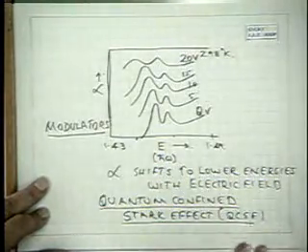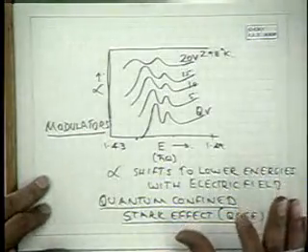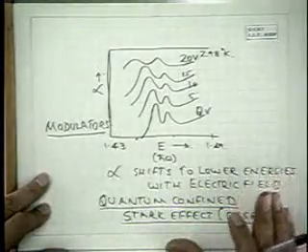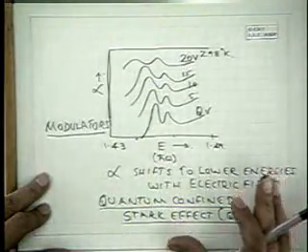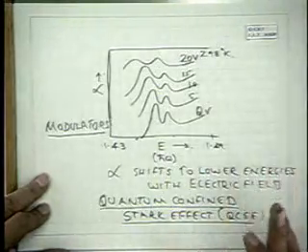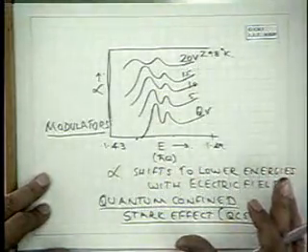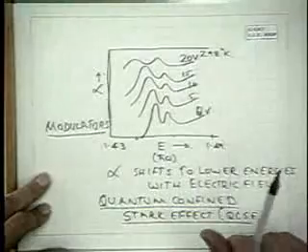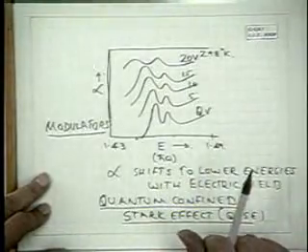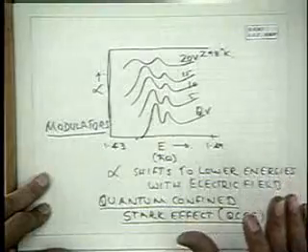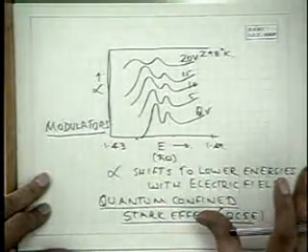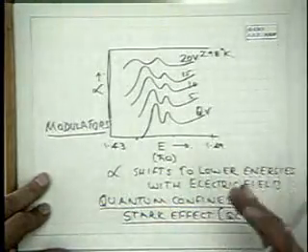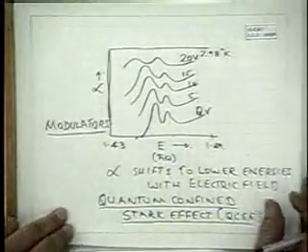And broadly speaking, this shows that the phenomena of optical absorption in quantum wells is different from that in bulk. One has much higher excitonic effects because the excitonic binding energies are larger. There are discrete transitions from valence band to conduction band depending upon the band structure. And later on I will also show that if you have wells or superlattices with strain built in, then the basic band structure can also be changed, and that would change the optical absorption as well as the luminescent efficiencies.